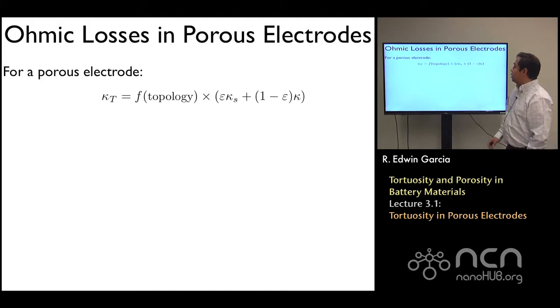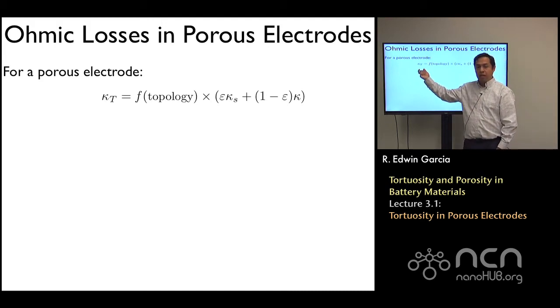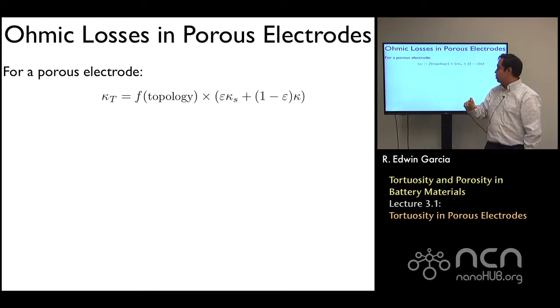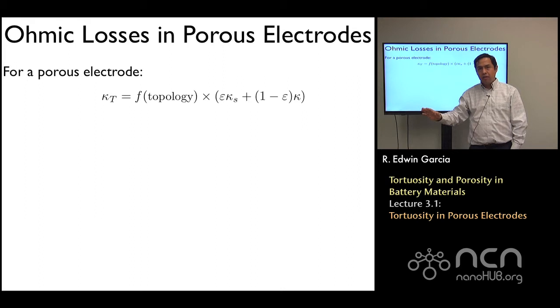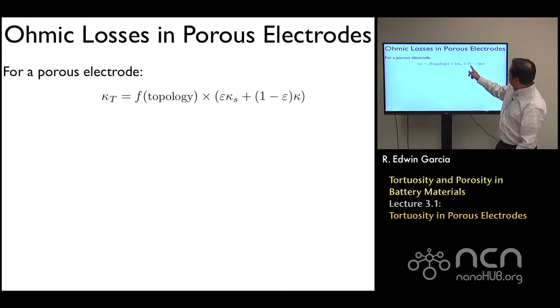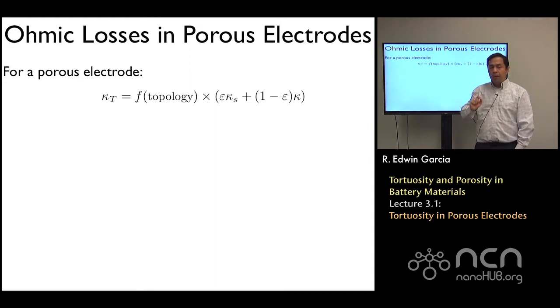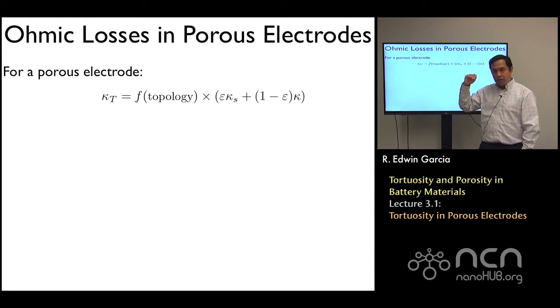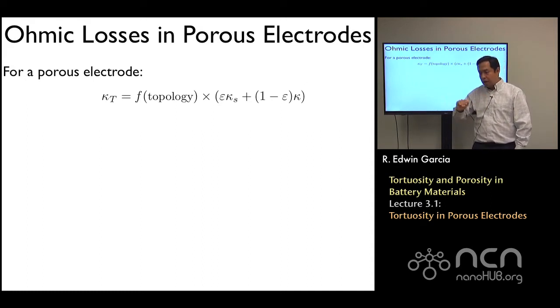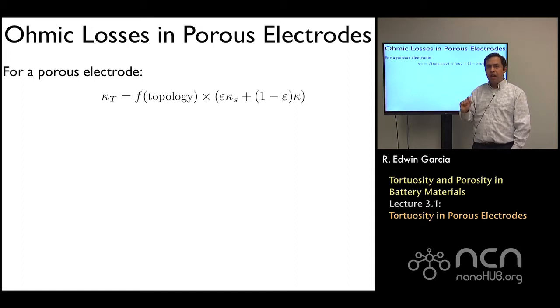The first thing we're going to do is quantify the total conductivity of that porous composite electrode. Typically what people do to a first approximation is think that the conductivity is a result of the conductivity associated to the particles modulated by the volume fraction of particles — which corresponds to one term — plus the conductivity associated to the spaces left between the particles, that is the porosity, which corresponds to the other term. If we had perfect layers of anode and electrolyte parallel to each other, it would really depend only on the volume fraction to specify the average conductivity of the system.